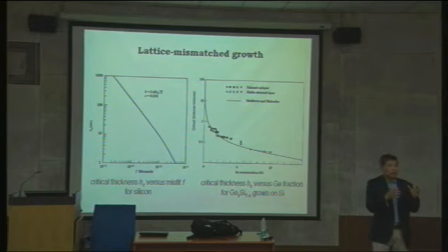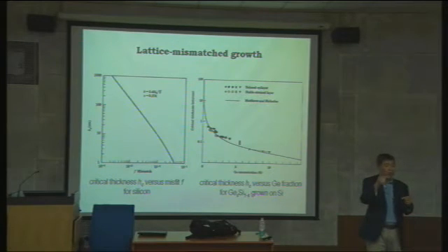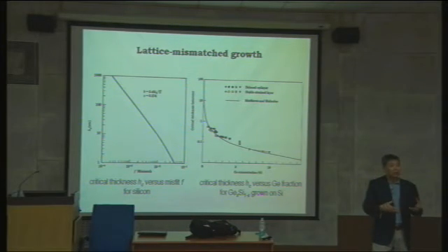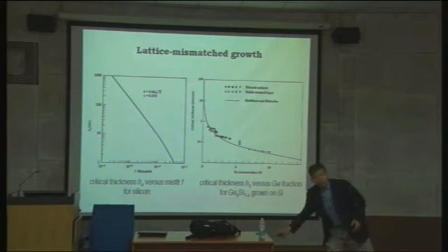Because energetically the thermodynamic final state is aluminum oxide, but it takes so long to get there, because the diffusion of oxygen through the aluminum oxide is so slow at room temperature. It takes millions and billions of years for all the oxygen to go in and make aluminum oxide. That determines the kinetics. Kinetics tells you the time scale involved, while thermodynamics does not consider time scale, only the final state. And here is the same thing. When you grow thin films and thermodynamically predict this number, it does not relax because you do not have enough kinetic energy to form the dislocation. With a strong barrier to forming dislocations, they don't form. So that's what we have to consider.